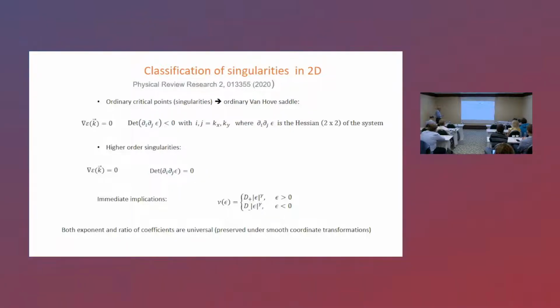And it is of the type kx squared minus ky squared that we know. If this determinant is 0, then we have a higher order Van Hove singularity. So the density of states diverges with an exponent if we set the Fermi energy at 0, so this gamma is negative. What we found is that both the exponent and also the ratio of the coefficients above and below 0 are universal and are preserved under smooth coordinate transformations.